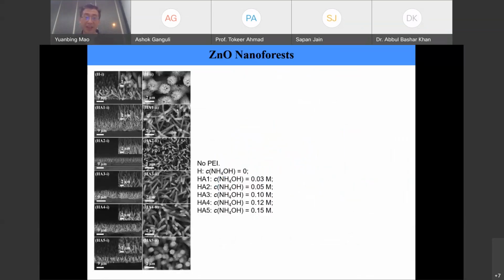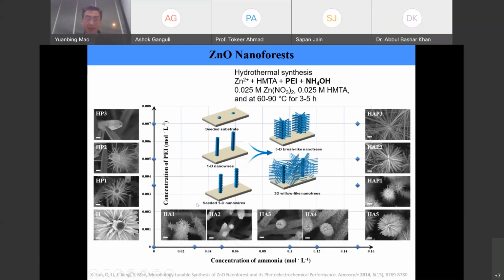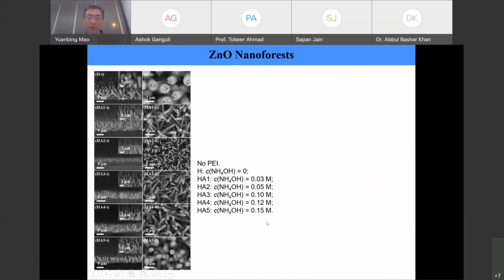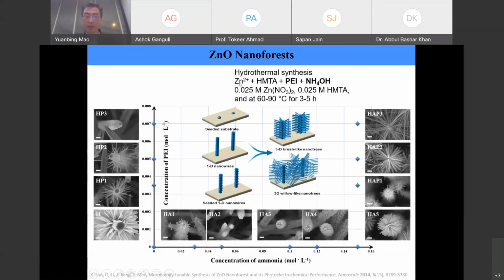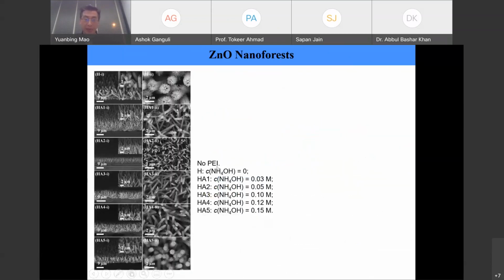And then, of course, to get this summary slide here, we did a few things I want to show you quickly, so you know where it came from. The first thing we did is we didn't add PEI. Here we have zinc nitrate and then HMTA in there. But with no PEI, we changed the concentration of ammonia, and you will see how the branches changed, and also how the original zinc oxide nanowire shape changed.